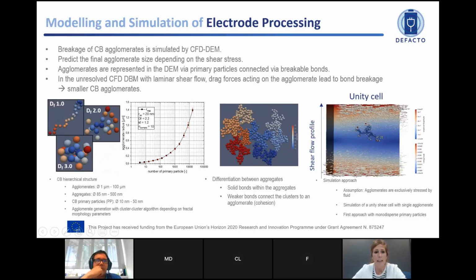And the agglomerates, which are represented in the DEM, are represented by primary particles connected via breakable bonds. So within the unresolved CFD-DEM with laminar shear flow, what occurs is that the drag force acting on the agglomerate leads to bond breakage, and this is provoking smaller carbon black agglomerates.